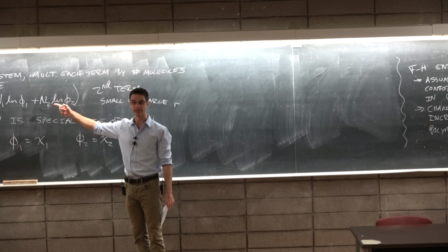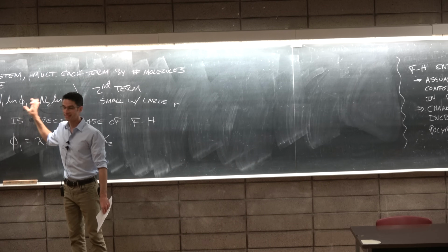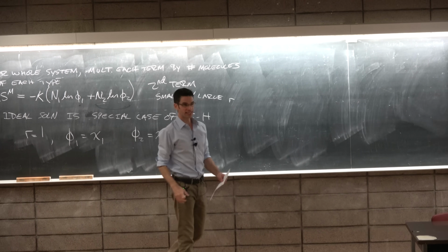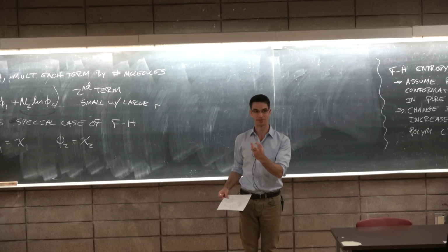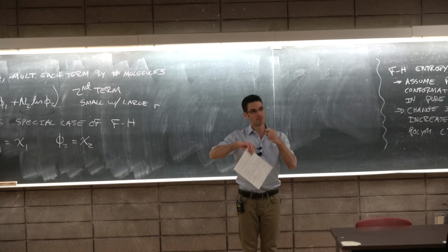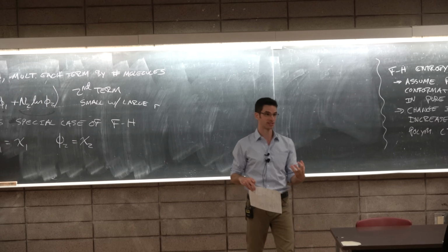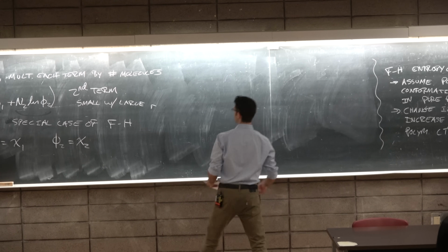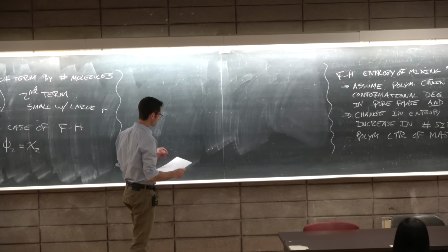Okay, now we need to take this, because this is just one part of the free energy that predicts the equilibrium phase behavior of a polymer-solvent mixture. This is just the delta S term. Now what about delta H? So delta H of mixing is no longer going to be 0, because we're going to say that the two different monomers or solvents, the argument works for different solvents as well as for polymers, do not have the same intermolecular forces and therefore don't have the same delta H.